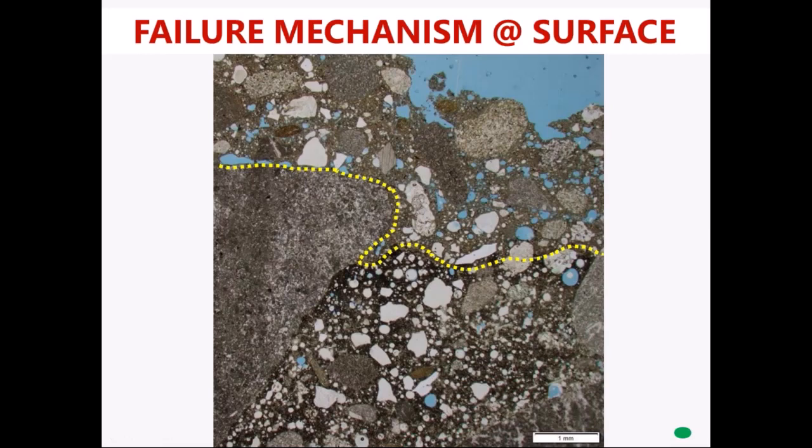And if this sample had gone through a winter, that paste wouldn't have survived a freeze-thaw cycle. It's just too weak. And all of those open spaces that we can see here in the uppermost paste that are now filled with air, when this was placed, those were filled with water. And so clearly the paste was too water rich. Without being there to see what did that exactly, I can't say, and I won't point fingers.